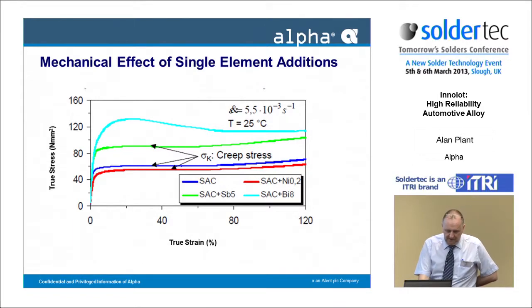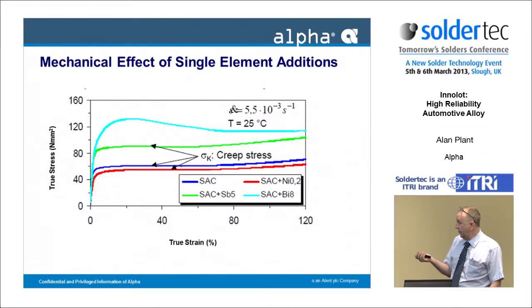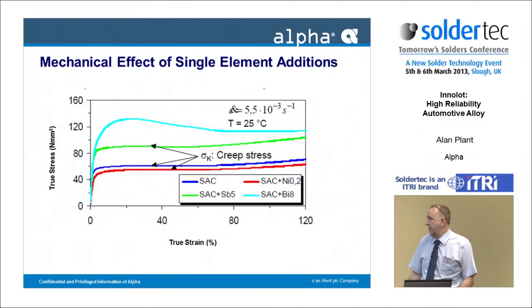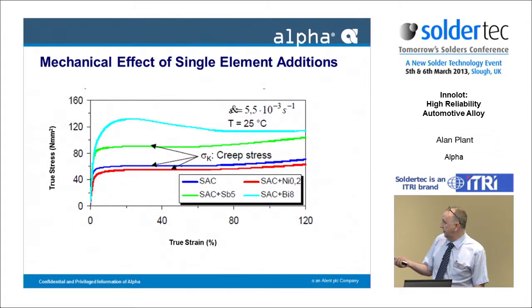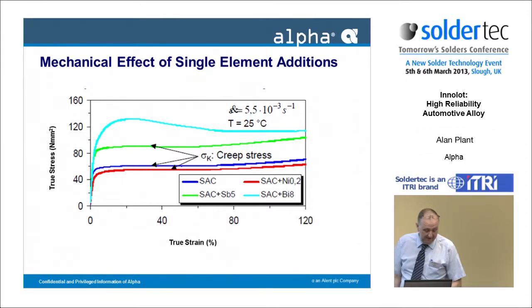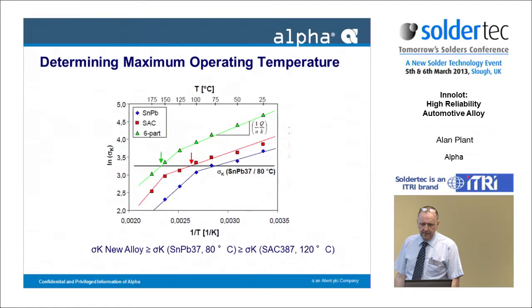Okay. So how were we going to choose how much and which of these we were going to add? So if we look first here at the creep characteristics, so this is just a SAC alloy, the base SAC alloy, and then we added each one of the elements, the working group did that. And we looked at the creep stress, and as you can see, the solid solution strengthening is improving the performance with bismuth and with antimony, and in this case the nickel is actually slightly reduced. Now I'm guessing that's because it mops up some of the, there's not enough copper in there, it mops it up, it's possible, I'm not sure of the mechanism, but that's what we had. So we had single element additions to make ourselves a quaternary alloy.